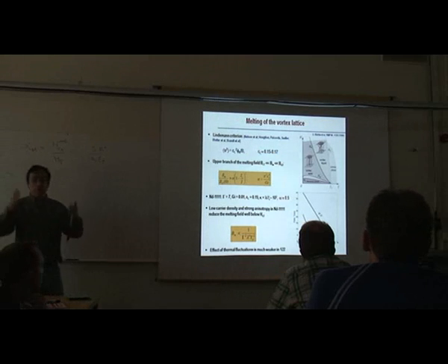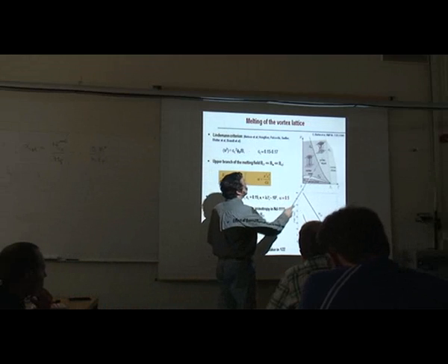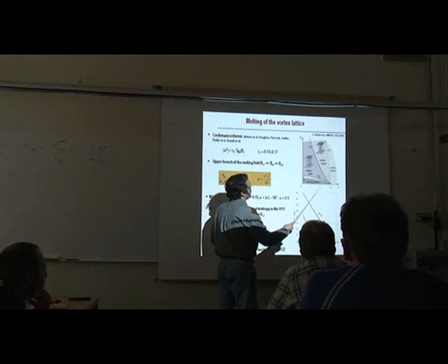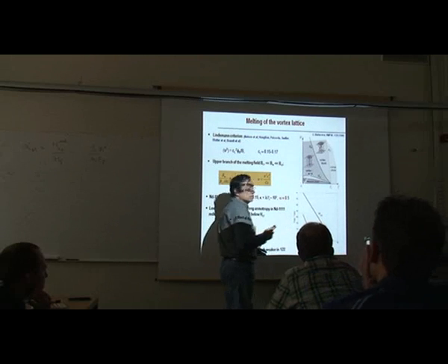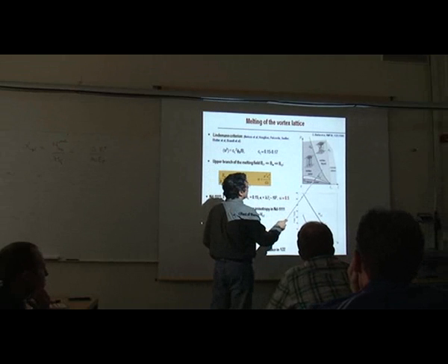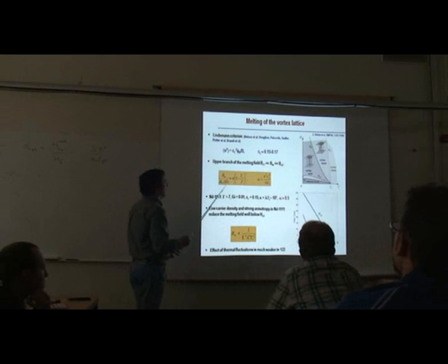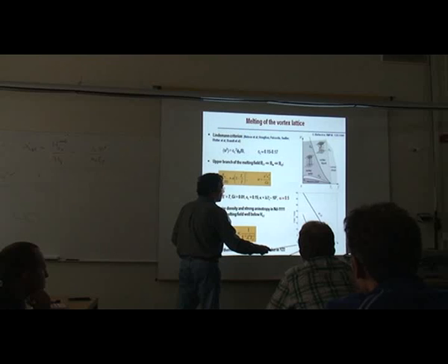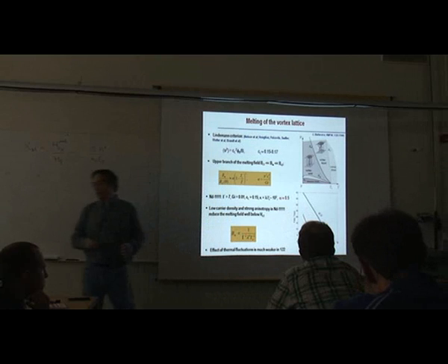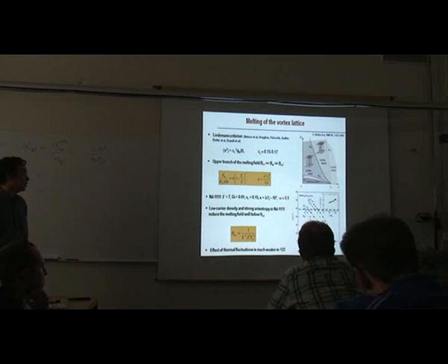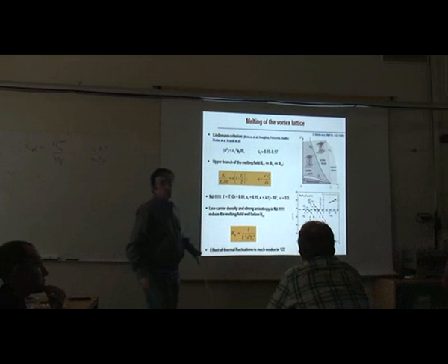So in cuprates, it's well known that the vortex lattice melts well below Hc2. Here's the phase diagram. This is the Hc2 line. We have a vortex liquid state here, as sketched here. And here we have some kind of vortex glass state with a random pin. But this line can be significantly lower than Hc2. And here's a formula which describes that. For the 1111 compound, that's what we have. We calculated this melting field, it's significantly below Hc2. In the lower Tc superconductors, here's the melting line, here's the Hc2, they're not very far apart.